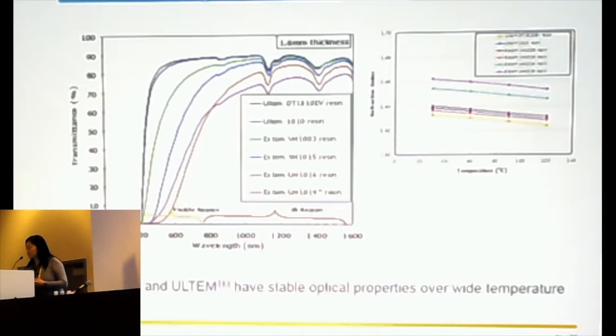And our material has pretty good transmission. If you compare to different grades, of course, the high temperature resins, even if they're transparent, they're always pretty yellow. It's nowhere near the polycarbonate grade that you use for your glasses, okay? But again, this is what we are trying to do, and this is the first case I wanted to show you.